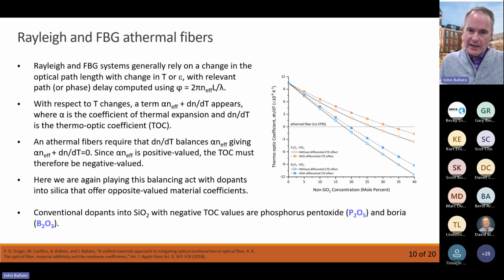Well, in this case, instead of looking at the Brillouin behaviors again, you look at the thermo-optic or thermal expansion behaviors for this type of sensor modality. But following a similar prescription, silica has a certain thermo-optic dn/dT, a certain thermo-optic value, positive. There are dopants into silica, like phosphorus and boron, so P2O5 or B2O3, that have negative thermo-optic behaviors. So as you dope silica with P2O5 or B2O3, the effective thermo-optic coefficient decreases. And you see that on the right, both for just a bulk material versus a core-clad fiber structure where you have thermal expansion taken into account.